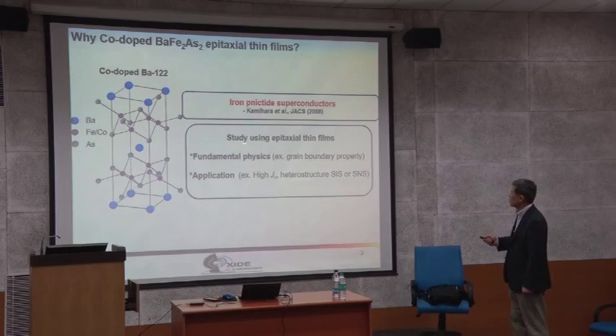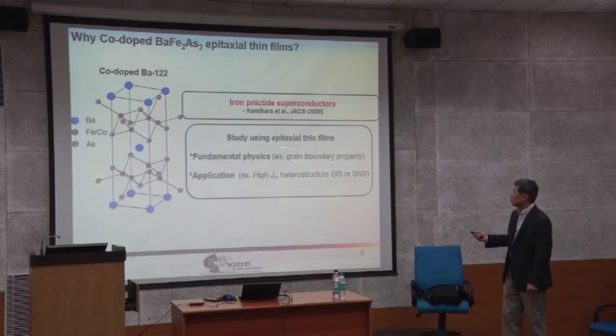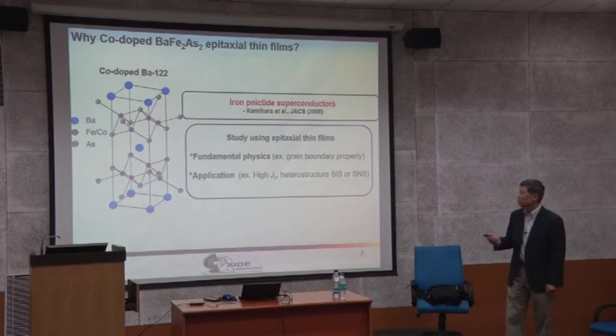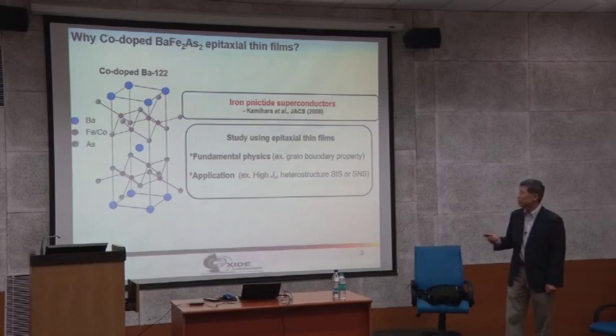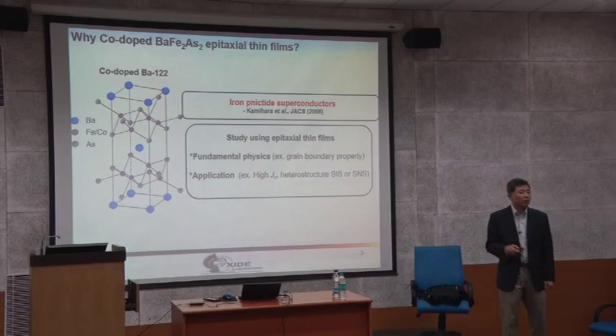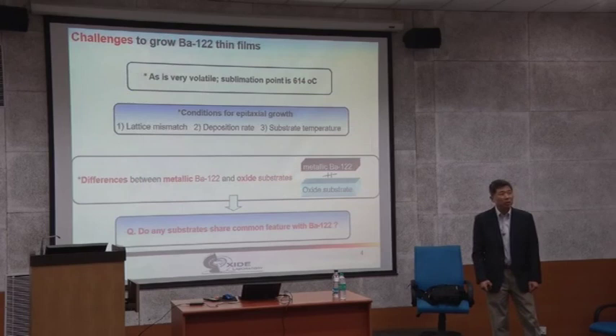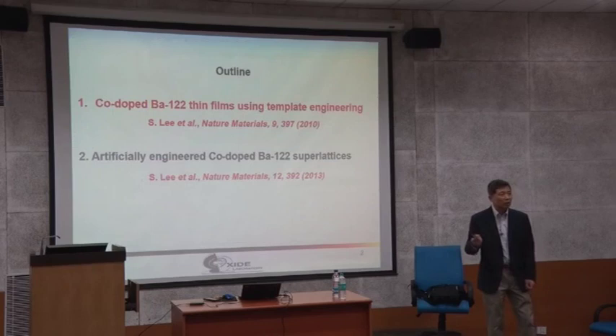This is similar to lanthanum copper oxide — LCO is an antiferromagnetic insulator, but when you dope it with barium it becomes a ~39 Kelvin superconductor — that was the first discovery of an oxide superconductor, the cuprate superconductor. This iron pnictide superconductor system was initially discovered by a Japanese group. There are many different families of iron superconductors: you have the 1-2-2 type, the 1-1-1-1 type with four different elements, and the 1-1 type like iron selenide superconductor.